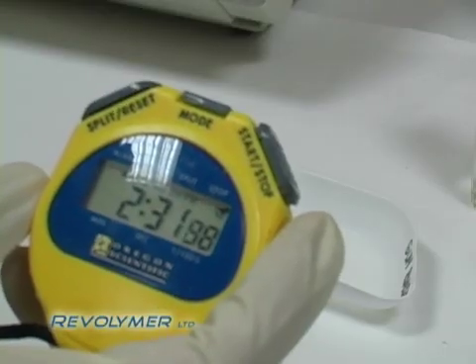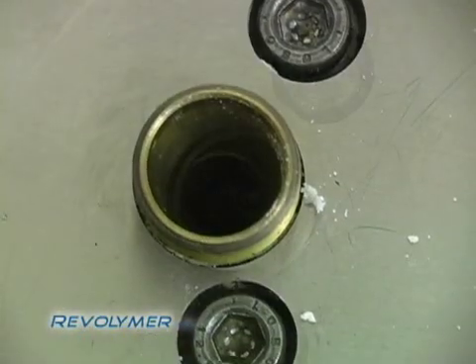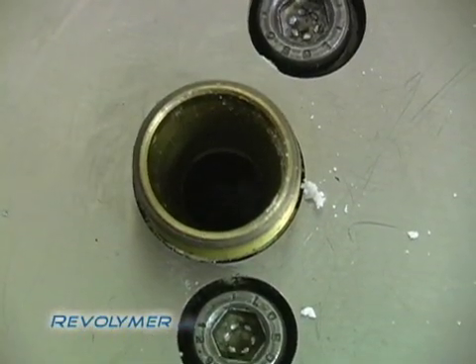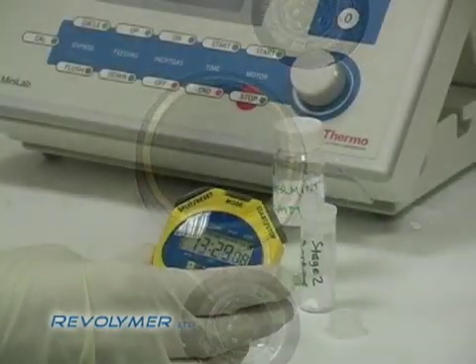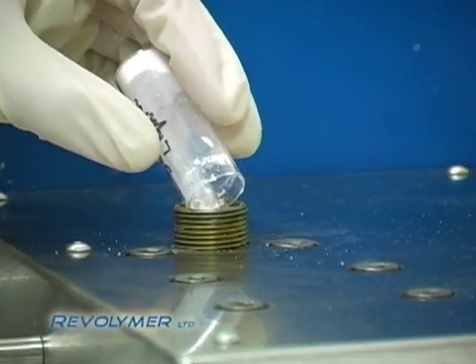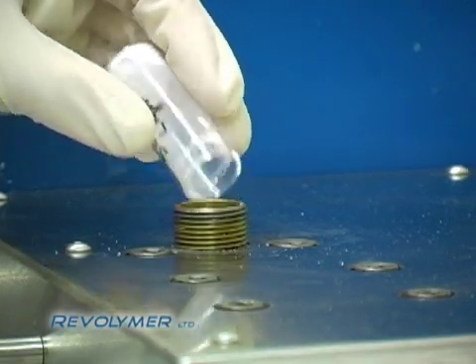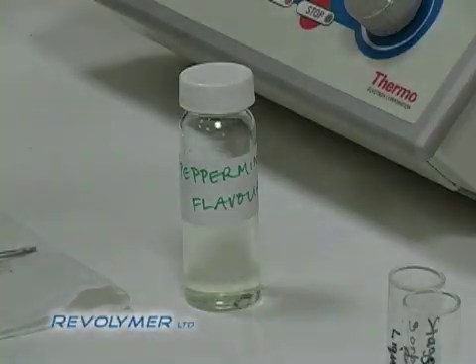We allow the extruder to mix the ingredients until we are sure they're homogeneously mixed. This is repeated three times, sequentially adding all the ingredients until we have the final gum base ingredients all inside the extruder. We then allow the machine to mix for a further half an hour to an hour depending on the formulation that we're making.